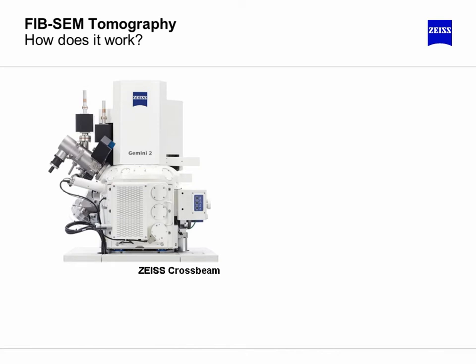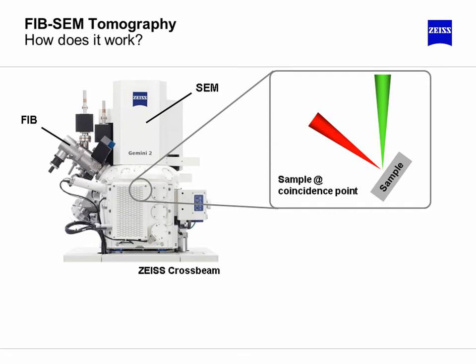How does FIB-SEM tomography work? Well, first of all, you need a two-beam FIB-SEM instrument or cross-beam instrument, like the one depicted here. On the top of the instrument, you can see the SEM column, and at an angle of 54 degrees, there is a FIB column mounted. The sample is in the chamber, positioned in the so-called coincidence point. The coincidence point is the point where both SEM and FIB beams intersect. In this position, the sample can be machined with a FIB with nanometer scale precision, and the process monitored with the SEM.